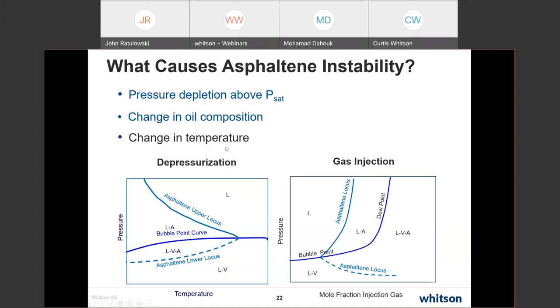But one thing to note with the temperature is a lot of times we take these samples and we're really careful. We do single phase downhole. We put them in a bottle. We bring them up. We make sure it's overpressurized, so maybe even above the reservoir pressure. But then we store them for a long period of time at ambient temperature. There is the possibility that the change in temperature going from reservoir temperature down to ambient in the storage will cause asphaltenes to precipitate in the stored sample.